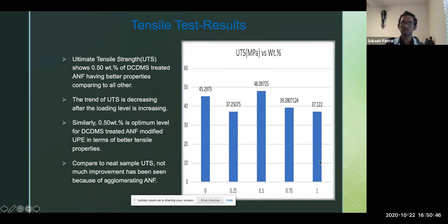But at 1 weight percentage, the tensile strength is 37.122 megapascal. So absolutely at 0.50, the tensile strength is far better than 1 weight percentage. After the loading level starts increasing from 0.5 to 1 weight percentage, the trend is decreasing in tensile strength, because of agglomerating aramid nanofiber.